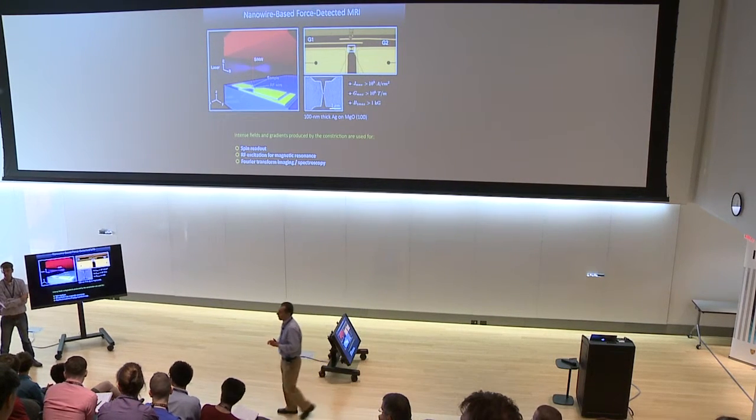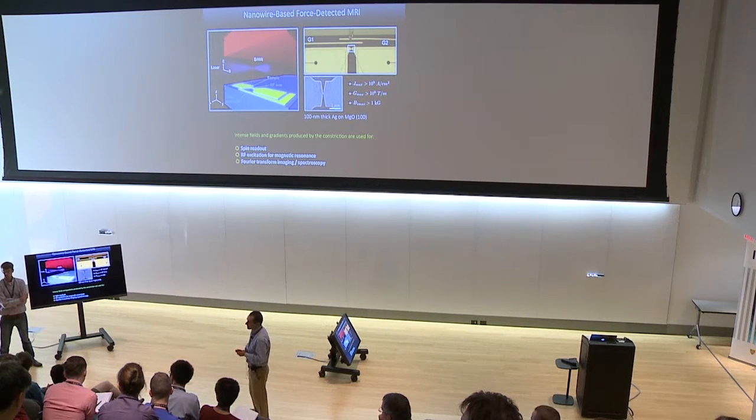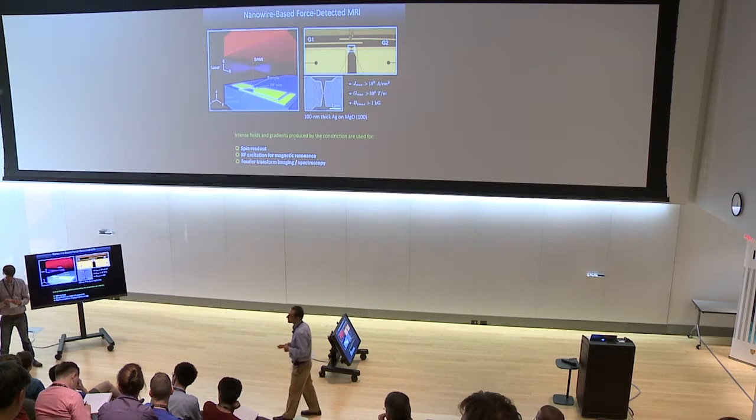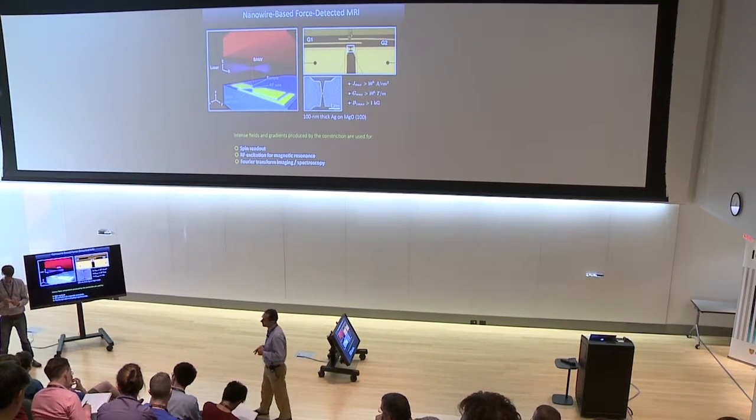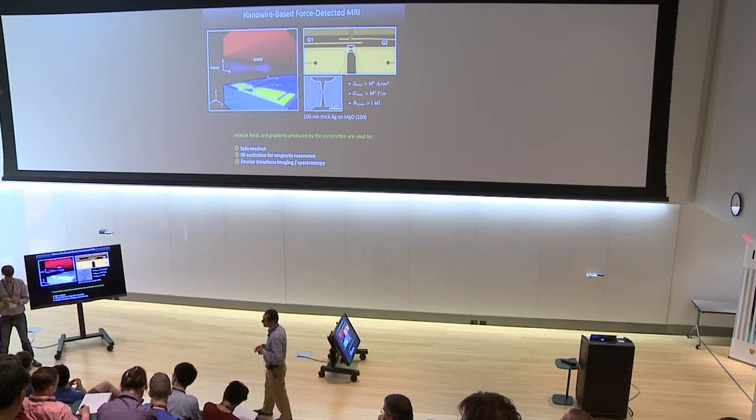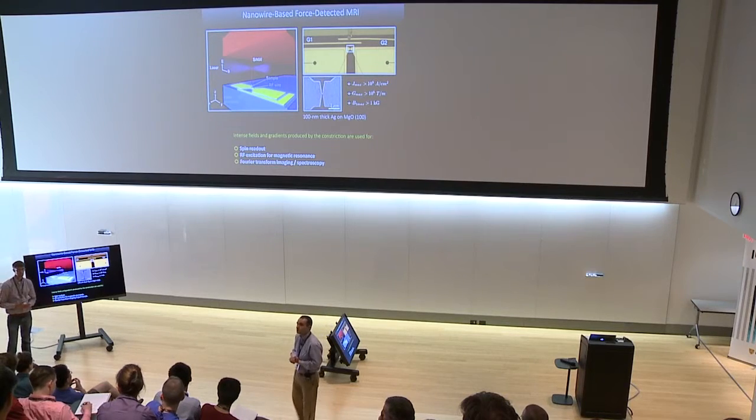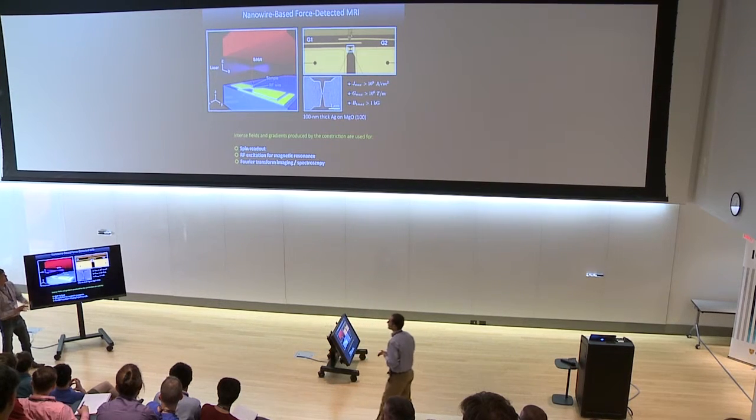Question: In the early days exploring cantilevers and non-contact friction, we found that having gold on the end of the cantilever was good, reduced charge fluctuation noise, but it did have eddy current noise when brought close to magnets. You always have a little gold particle. Answer: These don't actually. When we do this mode shaping, the thermal oxide is grown at a thousand degrees. The gold will just simply move. Prior to doing that, we actually ion milled the gold particles off. So there's just bare silicon.